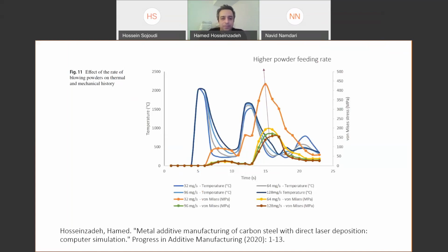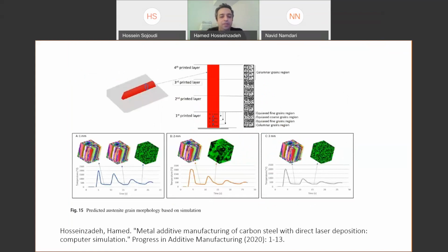So we can simulate the whole process. Because we can calculate the thermal history, the heating and cooling curve for each point in the sample, we can run mesoscale simulation, such as Monte Carlo, cellular automata, Potts model, or continuous ones such as phase field, and predict the local microstructure, grain structure, to see if it is equiaxed or not, if it is columnar or not.